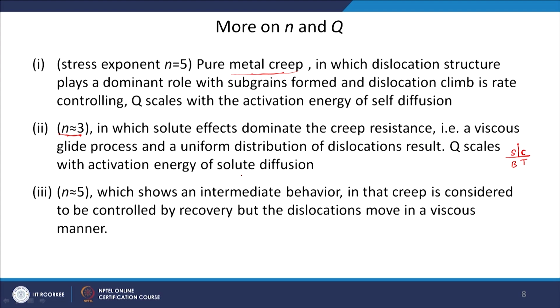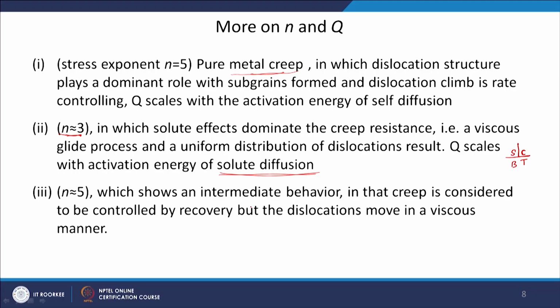Q scales with the activation energy of solute diffusion, because how fast solute will be able to diffuse, that decide how the dislocation is going to move, and that decides the creep rate. If n is equal to 5, which shows an intermediate behavior, in that creep is considered to be controlled by recovery, but the dislocation moves in a viscous manner. So, for different n, different Q, I can take a guess that what will be the dominant deformation mechanism which is taking place in the material.